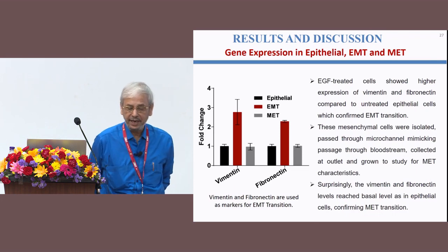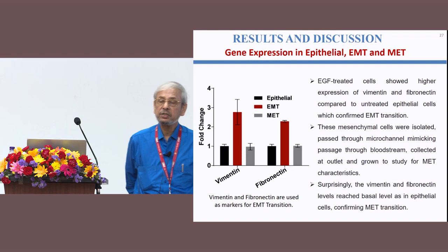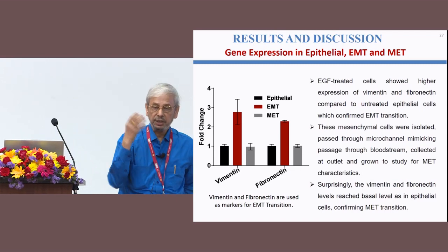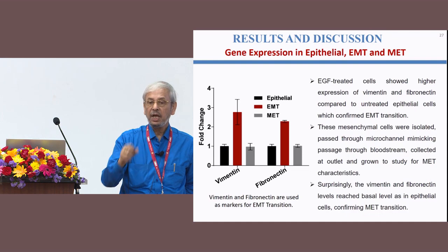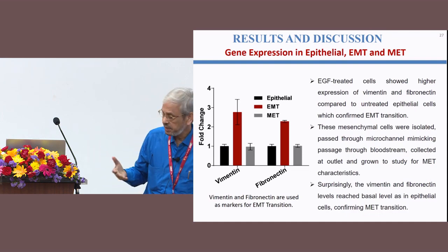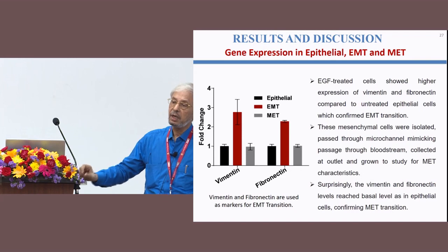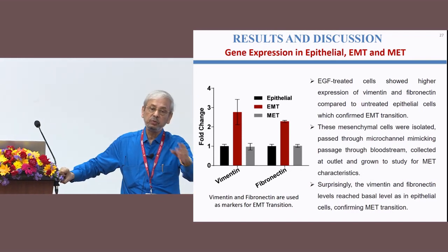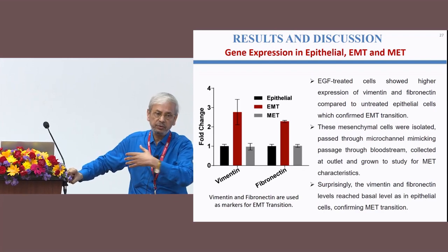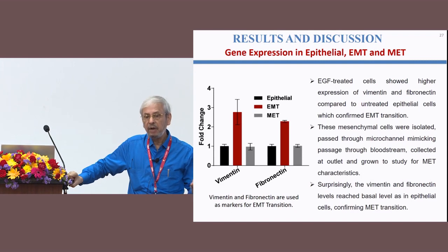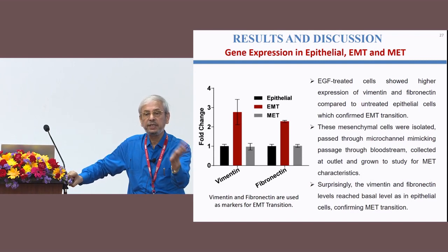It is definitely, I admit, not the same, because blood vessels or capillaries, the pulmonary capillaries, are a lot more flexible. So the effect should be less, right? We just mimicked it with PDMS, and to bring about that change, the amount of cross-linker was varied a little. If you have more cross-linker, it is more rigid. If you reduce the cross-linker, it is a little more flexible. Only that part could be done.